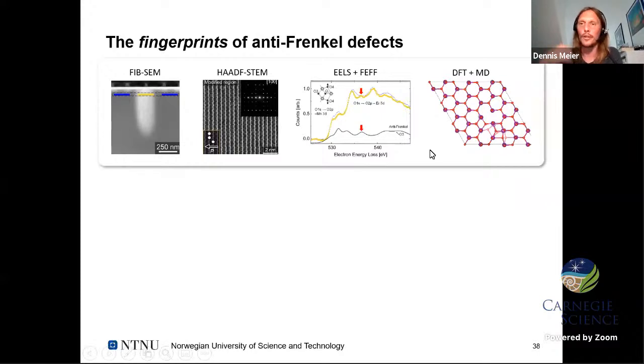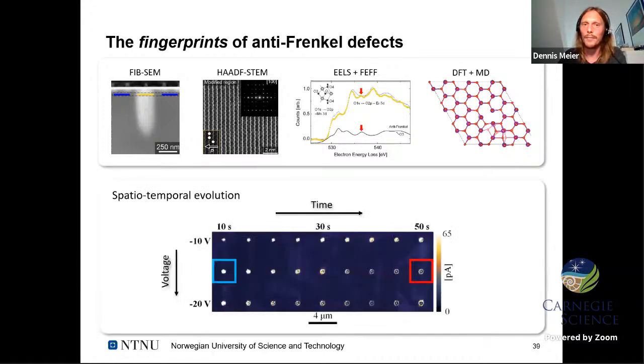But how did we now show that these are really anti-Frenkel pairs? Of course, we did a lot of different experiments. We used FIB-SEM cross-section to show that the effect goes several hundred nanometers into the material, not just the surface. We used STEM imaging to show that there is no impact on the crystal structure because the expansion and contraction from the oxygen just compensates. We used EELS to look for tiny features in the spectra to show that these defects are there, and also DFT and MD calculations to show that they are stable. All measurements, all data agreed that there are anti-Frenkel defects, but sometimes the simplest experiment is the most convincing one, and that's what you see here.